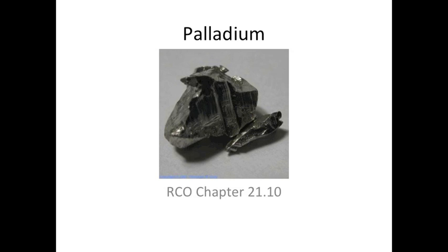Cold working increases its strength and hardness. At room temperature, palladium is able to absorb up to 900 times its own volume of hydrogen. Hydrogen readily diffuses through heated palladium, purifying the gas.